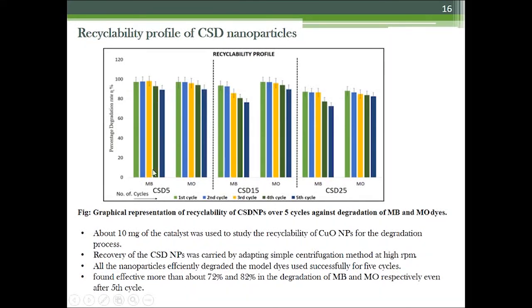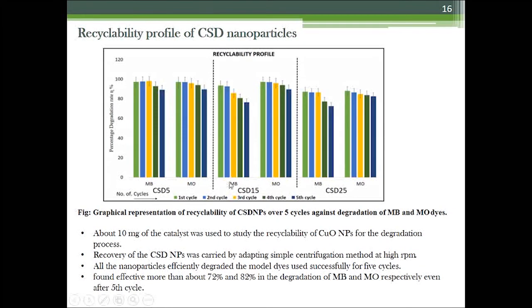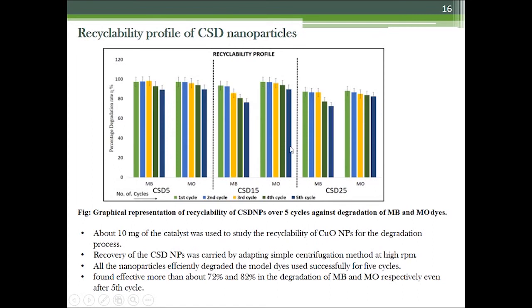About 10 milligram of catalyst was used to study the recyclability of copper oxide nanoparticles for the degradation process. Recovery of nanoparticles was carried out by adopting a simple centrifugation method at high RPM. It was found that all the nanoparticles efficiently degraded the model dyes used successfully for 5 cycles. Even after the use of 5 cycles, they have still retained the capacity of degrading the dyes. So all the nanoparticles were found effective, more than about 72 and 82% in the degradation of methylene blue and methyl orange even after the fifth cycle of their use.